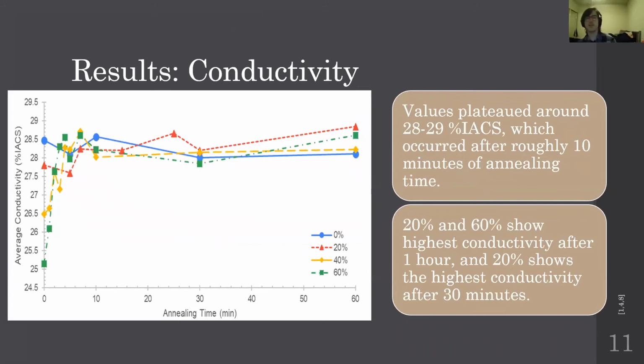Moving on to our conductivity values here, we can see annealing time versus conductivity in percent IACS. And as you look at the zero amount of time annealed, you can see that the 60% cold work has the lowest conductivity. That makes sense considering especially what Ryan said and what Chris talked about just before me, that this dislocation density causes a lot of problems because that's a lot of interference with electrons when they try to move through the sample.